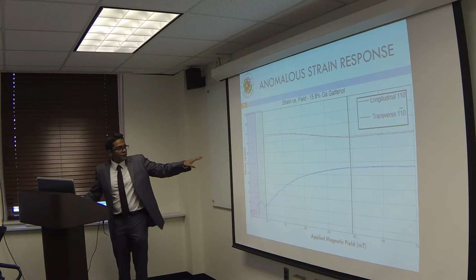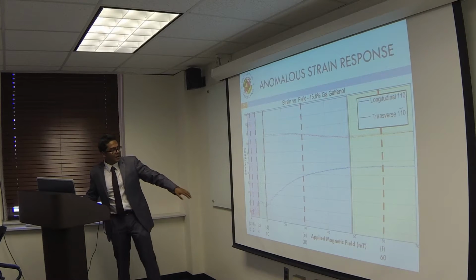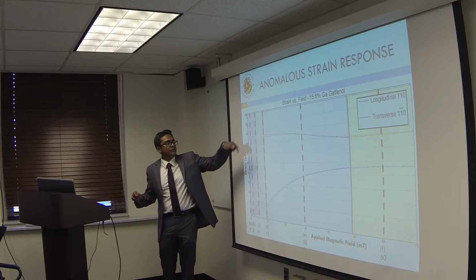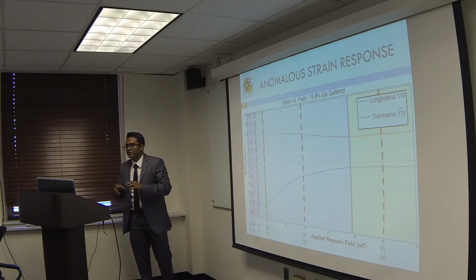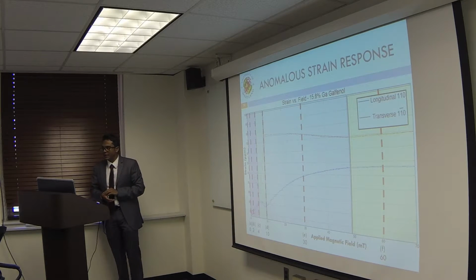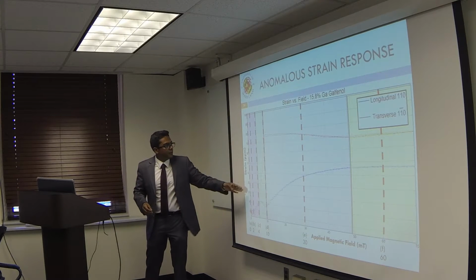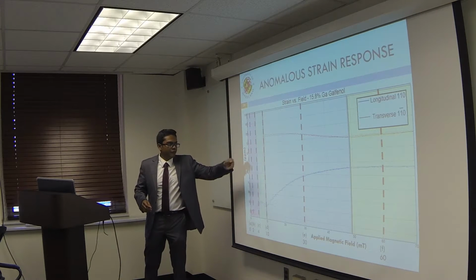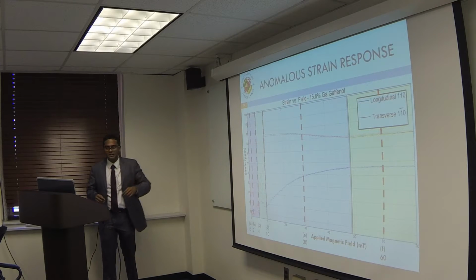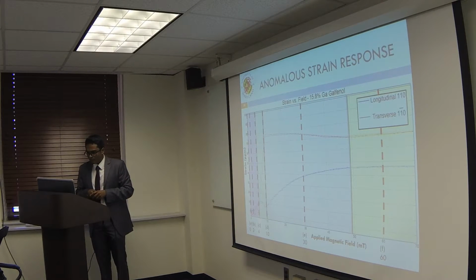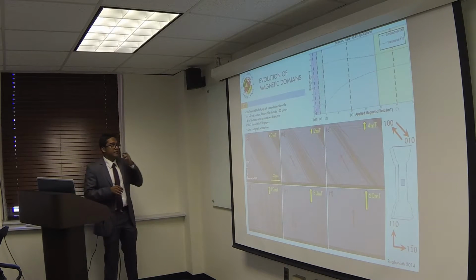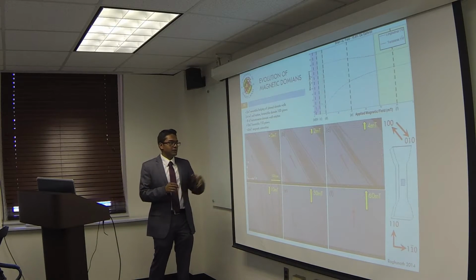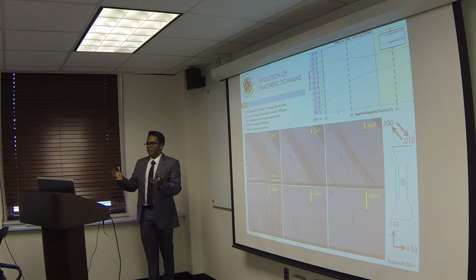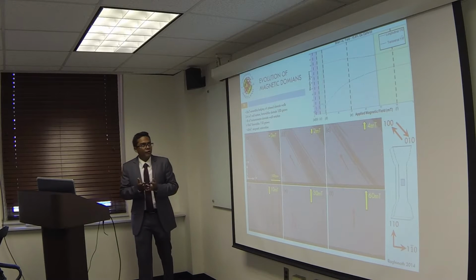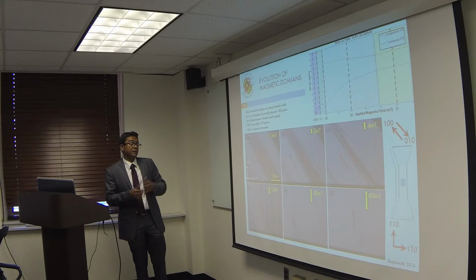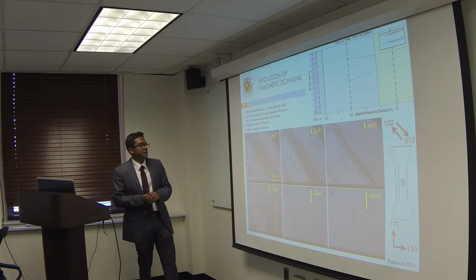So these are the 4 distinct regions that I talked about earlier, and the red lines depict the values at which I decided to take pictures or get the images of the magnetic domains. I wanted to take a picture at the starting and the ending point of every region that I have on the strain curve. And this was very fascinating. So for the first time, I was able to get magnetic domain images of Galfenol along the 110 with the magnetic field being applied along the 110 direction.